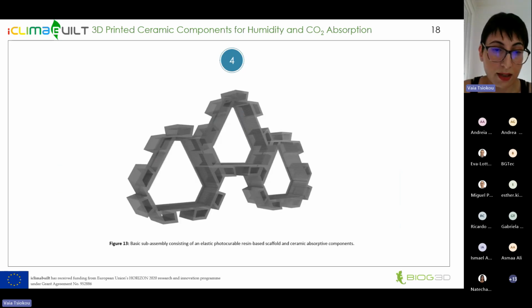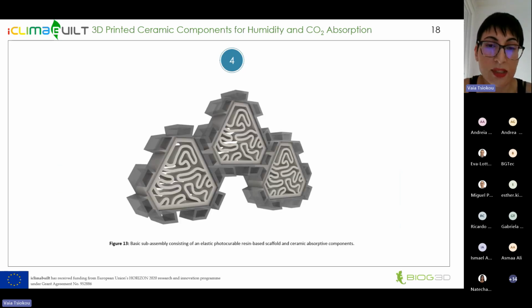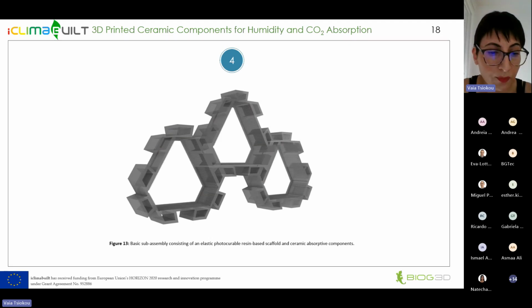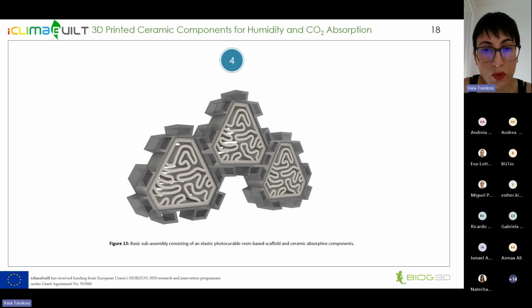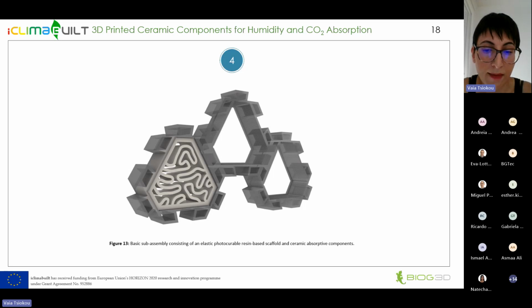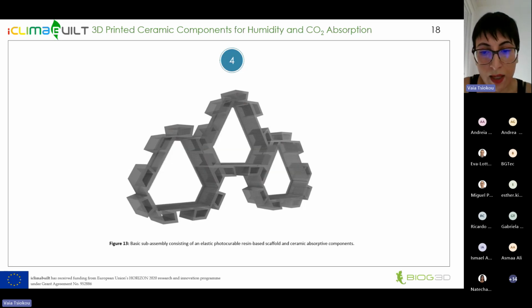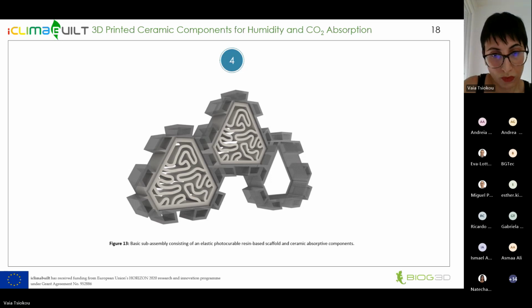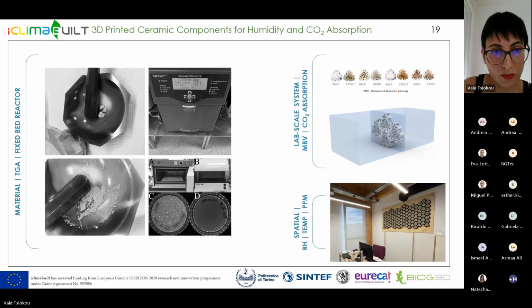As an optimized design, after several observations during the tests we have conducted, we have concluded to this design consisting of an elastic photocurable resin-based scaffold and 3 ceramic absorptive components. And as far as it concerns the testing of the test case, the same logic has been followed for testing on a material level.